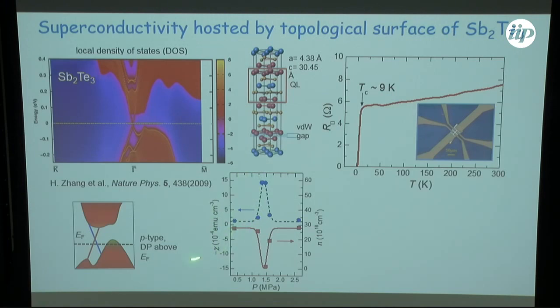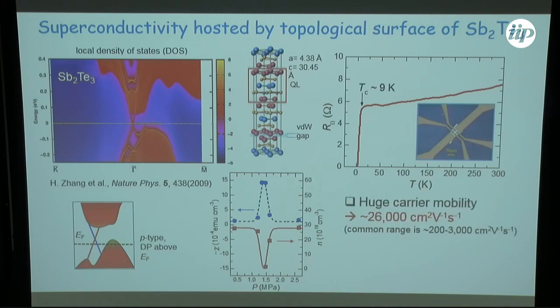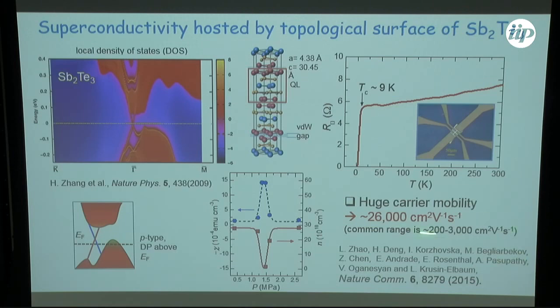This is measured by AC, and the other thing that we get from transport is that only in this region of parameters do we have huge mobility. In normal standard topological materials, the mobilities are of the order of, well, maximum 3,000. We have seen 10,000. We actually had bismuth tellurium bulk crystals which had 10,000, but this is really very large, and outside this region the mobility is less than 1,000. So suddenly we have access to this extremely mobile electron gas.